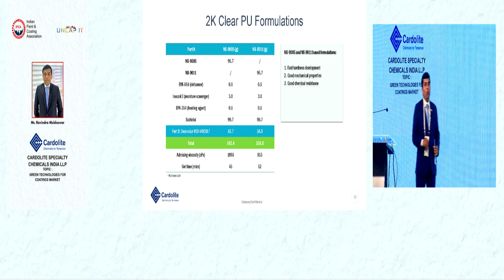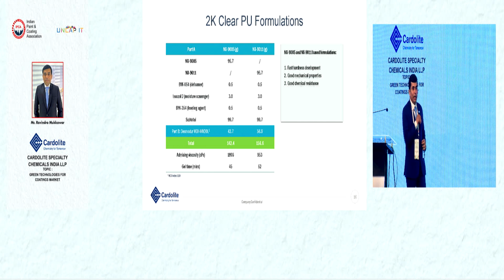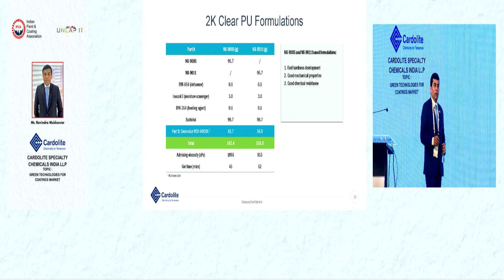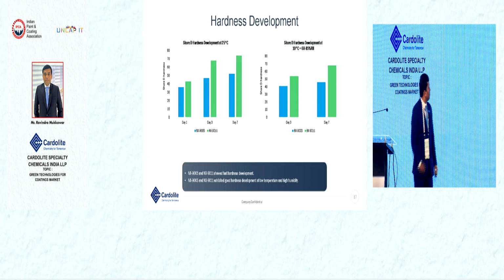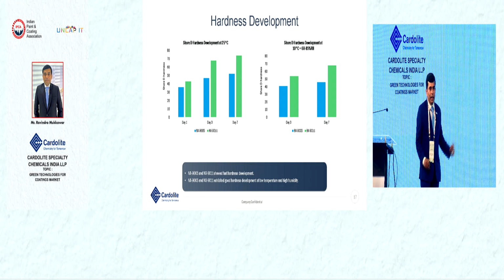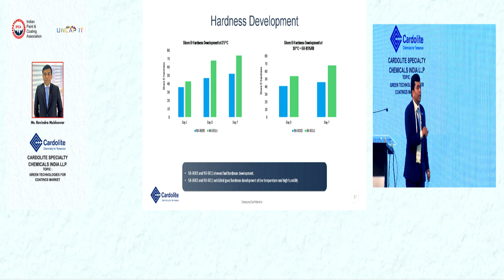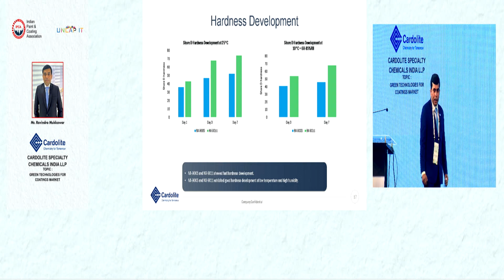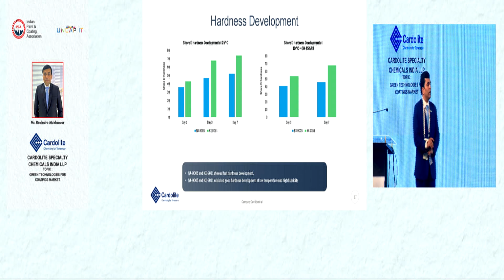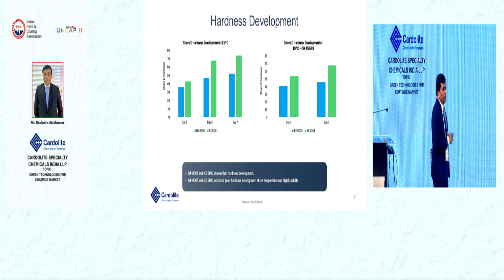So this is one of the formulations we developed, and we checked it in clear formulations and it gives fast cure, good hardness development properties, and good chemical resistance. We checked the hardness at 25 degrees; within 3 days it goes to 40, even for 9005, and after 7 days it will be 65 to 70 Shore D. Even at 10 degrees and 80% relative humidity, this product will also work fast. So even at 10 degrees it works.